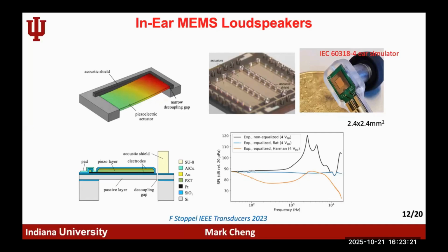The first one, you are increasing the volume of the enclosure, and those kinds of enclosures will help, because when you have a membrane vibrating at low bass, the radiation from the front and the radiation from the back are 180 degrees out of phase, so they will cancel each other. So you actually need some acoustic design to try to absorb that reflected sound. This is the one thing they came up with, a COMSOL simulation and an optimized structure.